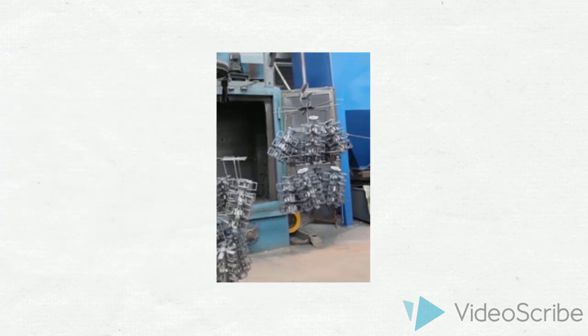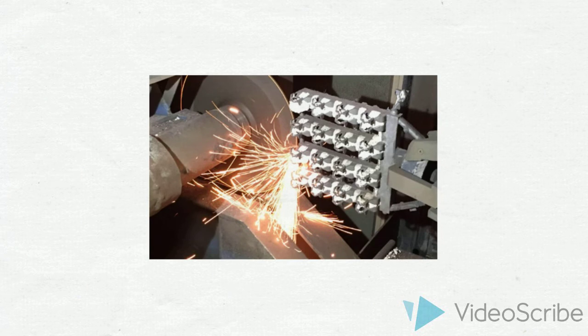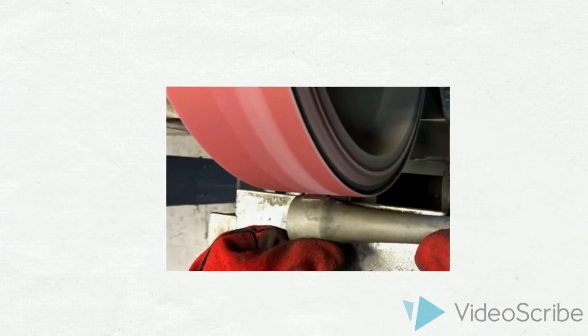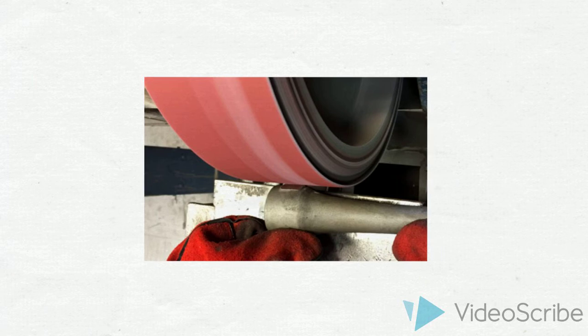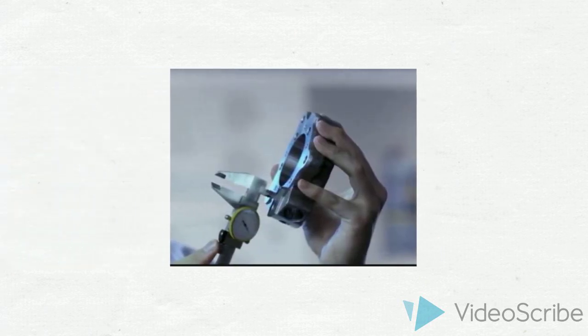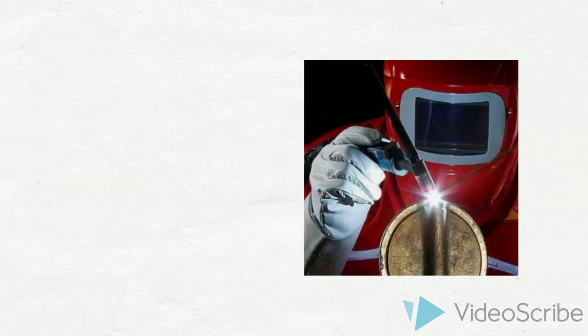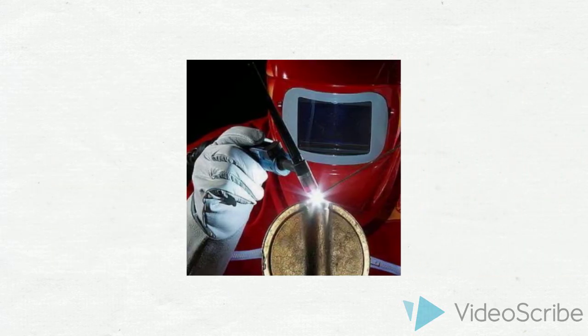With the bulk of ceramic mold material removed, the whole thing is shot blasted clean and the parts are cut from the sprue system. Following cutoff, the castings have the gating witness ground off. This is a stub of metal left from the cutoff operation. Immediately after the gate grinding operation, castings are visually inspected, marked for traceability, and any rework is performed, which most usually involves some degree of weld repair.